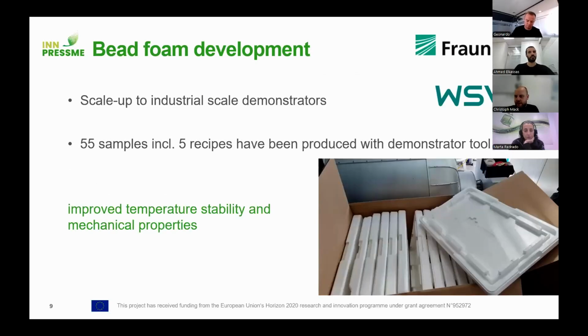Then we did the upscaling together with our industrial partner. So Fraunhofer provided the material, 5 recipes in total, in a larger amount. WSVK could produce 55 samples on their demonstrator tool, which were then again analyzed to check which was the best of these recipes. And in the end, we achieved improved temperature stability and mechanical properties at the same time, which was also the goal of our development.